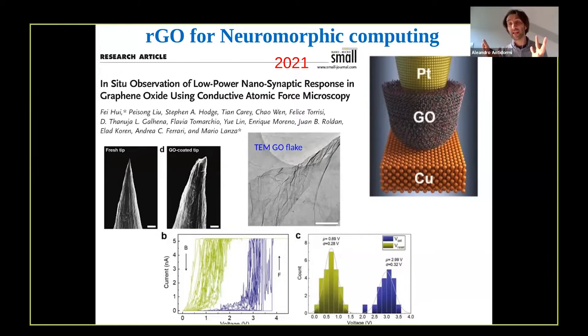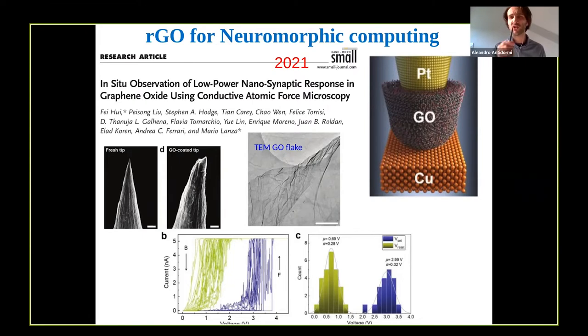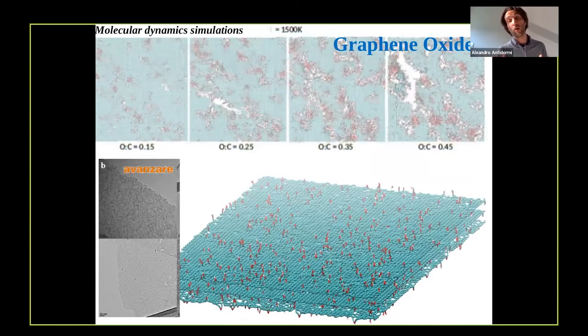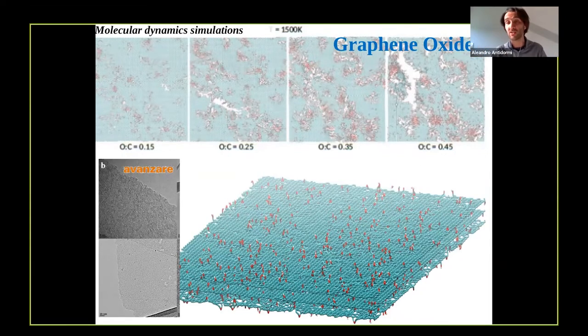The basic physical explanation for the change of resistance in graphene oxide relies on the migration of oxygen ions. When you apply a voltage, oxygen ions from the graphene oxide move towards one of the two electrodes, and this allows the change of resistance to take place. This points to a very important question: trying to understand how the properties of graphene oxide change and are affected by the amount of disorder or oxidizing agents in the material.